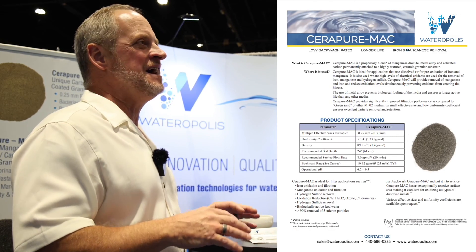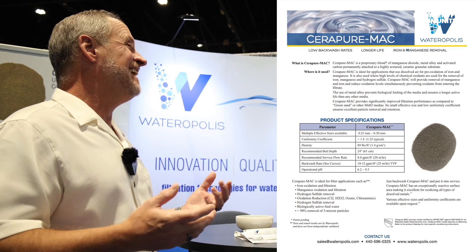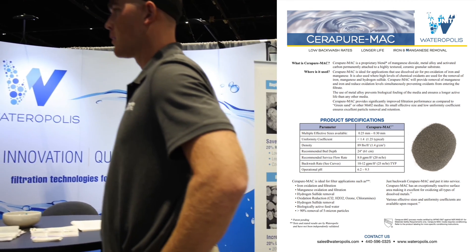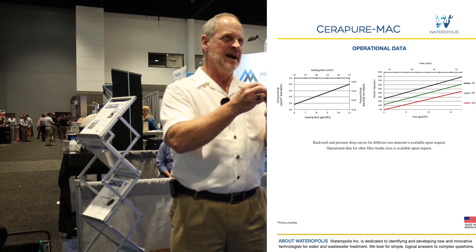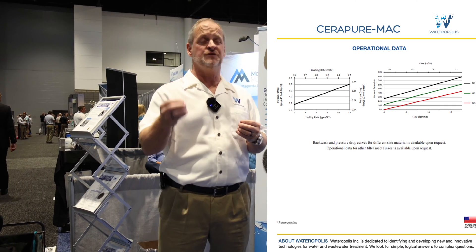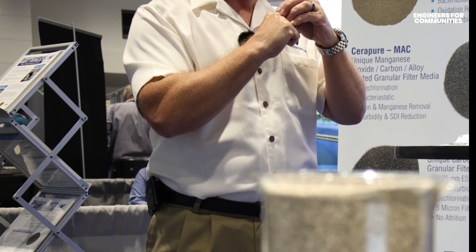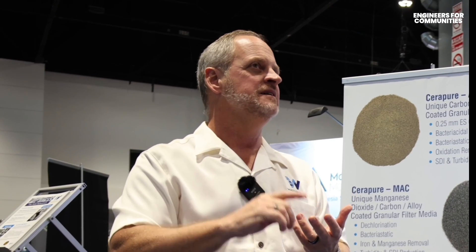Manganese is a little more difficult. You sometimes have to stand on one foot, pat your head, and wave a magic wand because manganese can be a little fussy. We've learned how to optimize products and put a reactive surface on those products. Manganese often needs a catalyst — you need an active surface and the manganese has to react with that surface, then you precipitate it on the media until you can backwash it out. There are no less than 16 different potential crystal structures that occur when manganese is oxidized, and that crystal structure is pH dependent, temperature dependent, and time dependent — so it's not as simple as people put it out there to be.